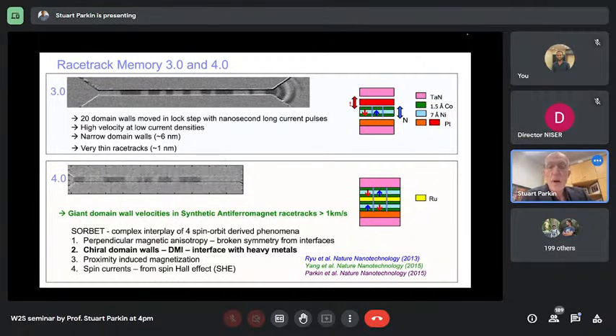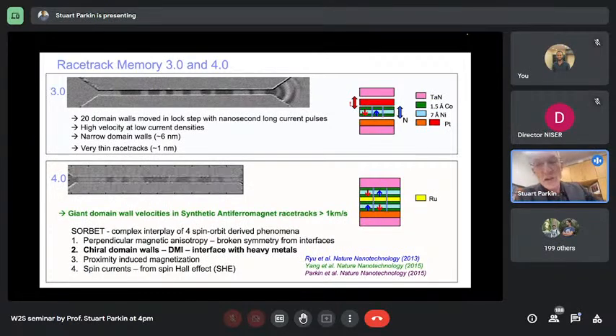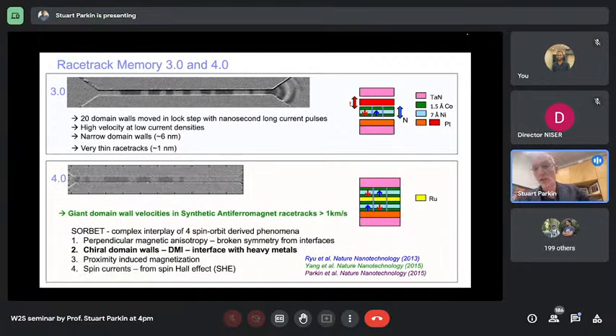And again, recently we published earlier this year some new materials, some 5D transition metal aluminum alloys, in particular iridium aluminum, where the spin Hall angle is more than 10 times larger than in platinum. And therefore, because the efficiency of generating spin currents from the charge current flowing through these new materials is so big, it means we could use currents to move domain walls, which are 10 times smaller for the same velocity.